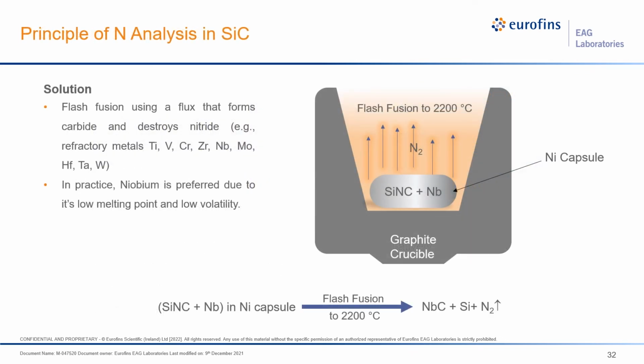The solution can be found by using a catalyst which can form carbide and destroys silicon and carbon nitrides. Refractory metals can play this role. Due to its low melting point and low volatility, niobium is a preferred catalyst. In this method, silicon carbide sample is packed in nickel capsule along with niobium flux. Using graphite crucible, the mix is then flash heated up to 2200 degrees Celsius. The outcome would be mostly niobium carbide, silicon, and nitrogen gas, which can be analyzed.